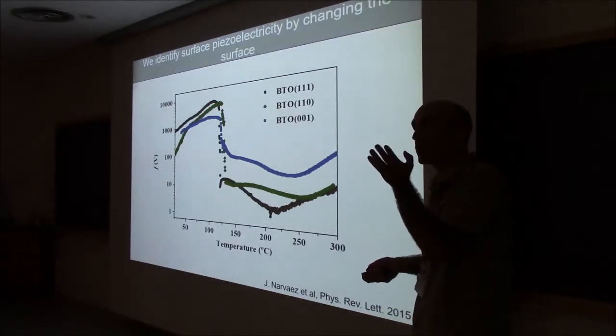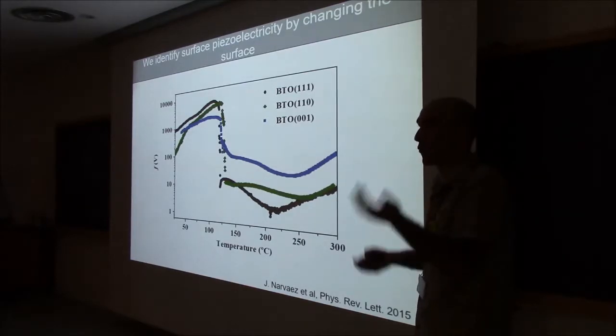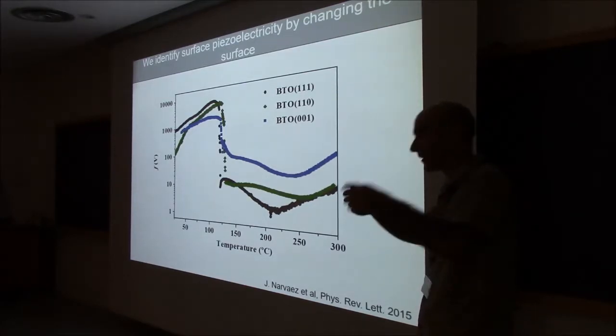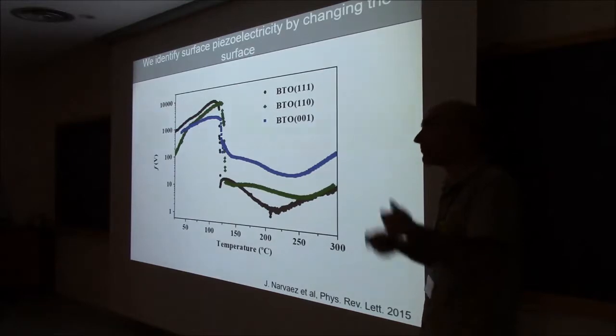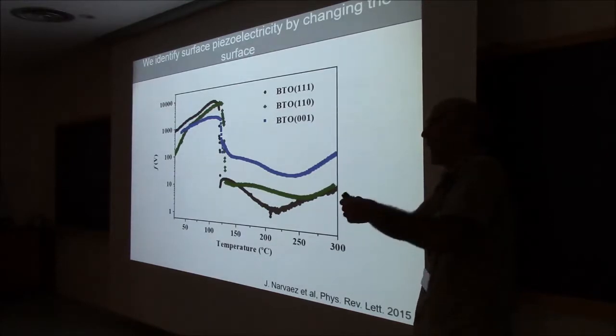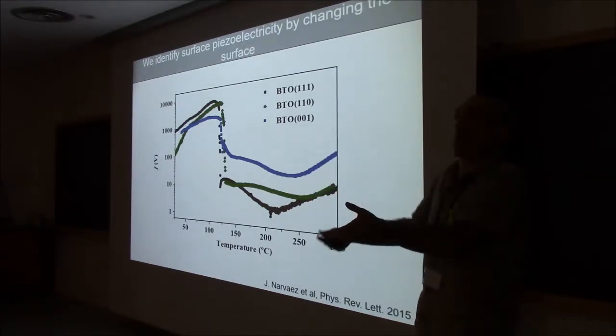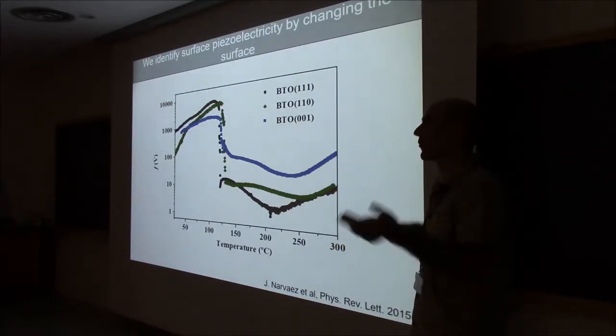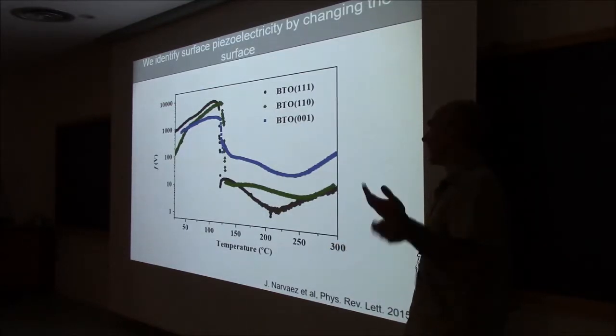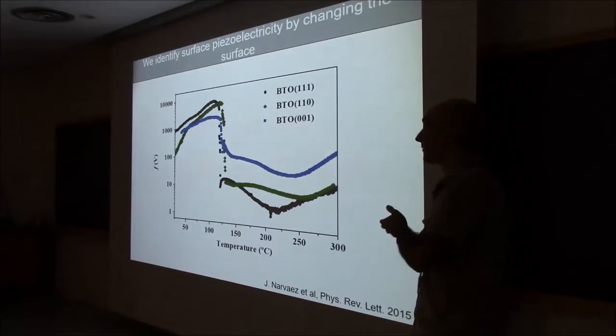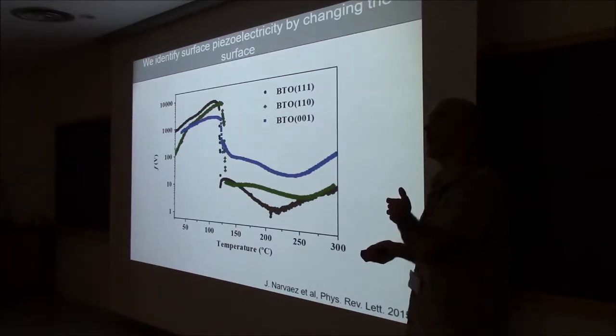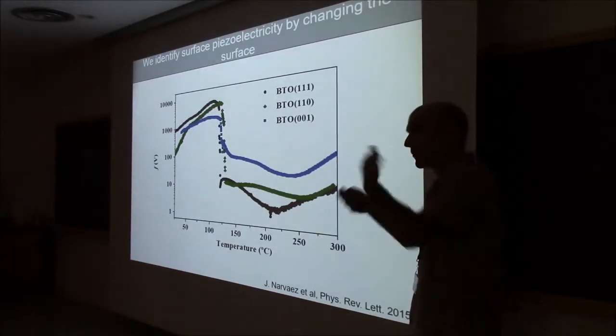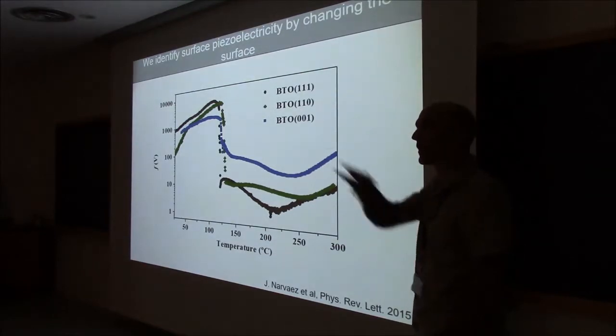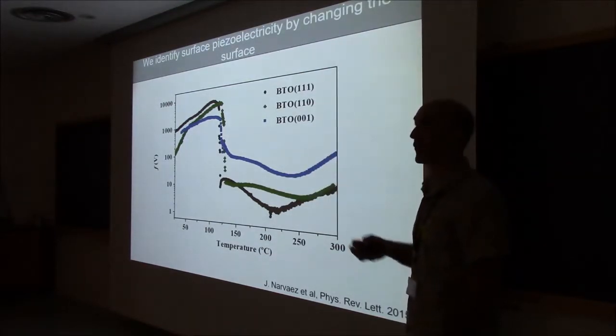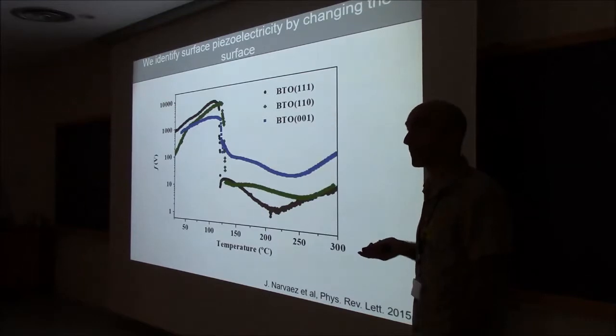Typical currents that I measure are of the order of nanocoulombs. So if you take a single crystal of BTO, you bend it, the amount of bending that you can have, and given the size of typical crystals that you can buy, you measure currents between picocoulombs and nanocoulombs. If you are very lucky, or if you measure semiconductors, and I will get to that in a minute if I can, you can measure bigger currents of the order of microcoulombs. But that's kind of the order of magnitude in which we operate, and we measure it by a lock-in amplifier.